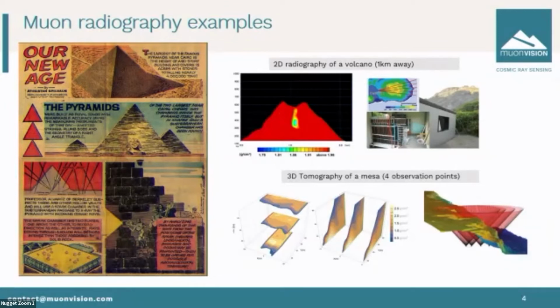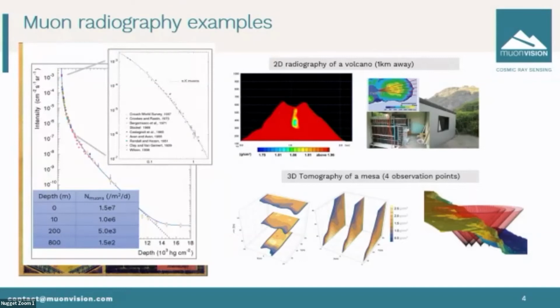You may argue, if this is so good, why is it not so widely used? Well, the reason is that this is a passive measurement. And if you look at cosmic ray particles, cosmic ray muons, although this is extremely well known to a physicist, the fact remains that their number quickly decreases. So this table is for density of material, with the density defined in hectograms.